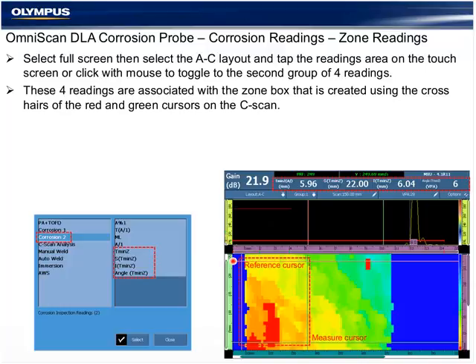If I create a zone with the crosshairs of the 2 cursors on the C-scan, within the zone I can see that the lowest reading was 5.96 millimeters, and it occurred at 22 by 6 millimeters on A-scan, or virtual aperture number 6. I could go look at that individual data point.